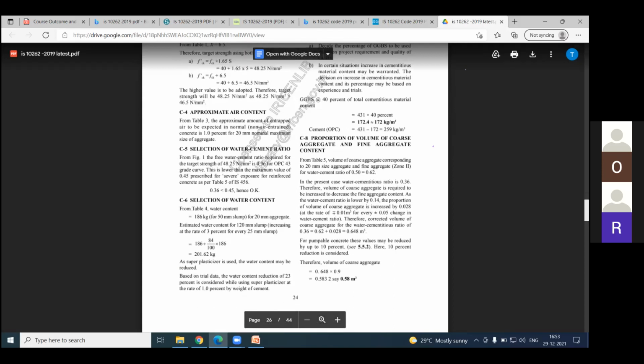Okay, I will come from the water cement ratio. First we have to fix the water. For 20 mm maximum aggregate, water is fixed for a 50 mm slump at 186 liters. But as I said to you, for every 25 mm increase in slump, we need a 3% increase in the 186 liters. If you want a 100 mm or 125 mm slump, you can calculate here. For every 25 mm increment, you increase 3% of water in 186. Then you will get the water content.